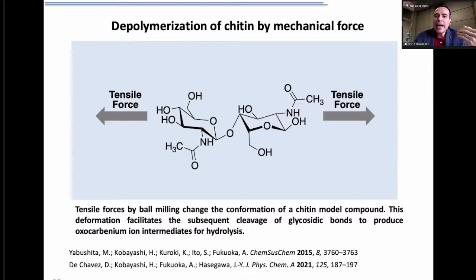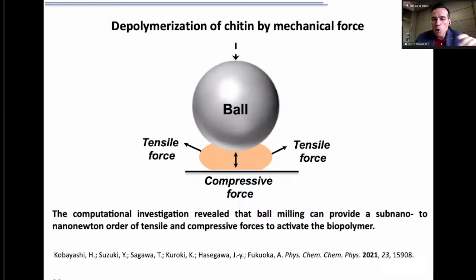So meaning that somehow, apparently, by ball milling, you can induce tensile forces, which can then bias a reaction mechanochemically. If you consider a ball collision, and this is what some people did, well, when you have a ball colliding against another ball and the sample happens to be in between, or a ball collides against the inside wall of a milling container, well, you will have compressive forces. But also, there is a portion of tensile forces that appear by ball milling. And precisely, they demonstrated that those tensile forces, despite being at the sub-nano-Newton scale, can add up and facilitate the cleavage of the chitin.